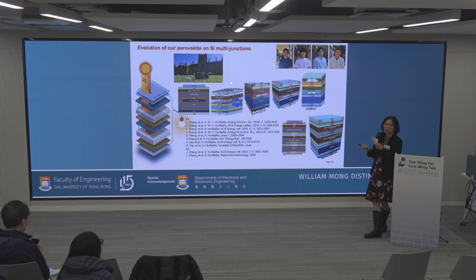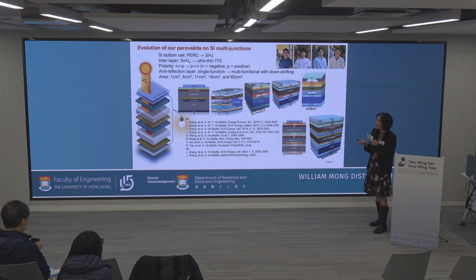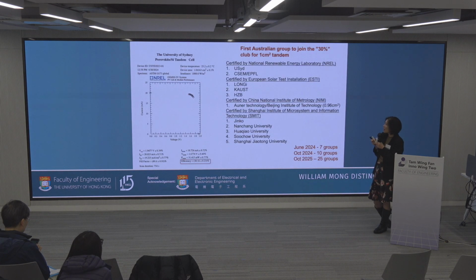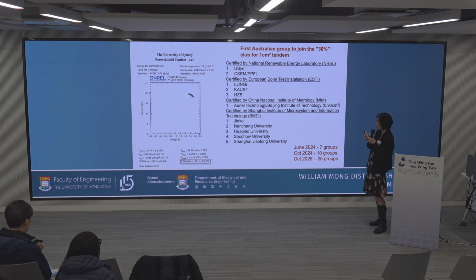So in our group, we do the same thing. We have evolved from PERC to heterojunction. The quality of the figures improve, and we're also looking at going from double junction to triple junction. So we also have moved from NIP to PIN, and I'll talk about why in the next slide, or the next slide after. So in 2024, we were able to get our 1 square centimeter cell certified at 30%. That year, there were 7 groups who were able to do it. And by October, there were 10 groups, and then 1 year after, 25 groups. And I won't be surprised now, there may be 50 groups who are able to get a 1 square centimeter perovskite-silicon tandem cell certified at 30% efficiency.